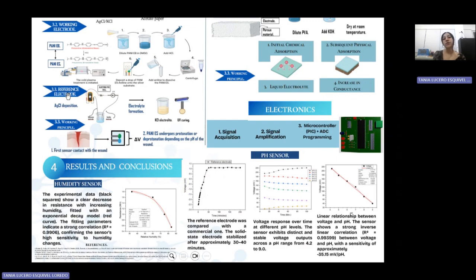Then for the reference electrode, there's a deposition of silver chloride, and from an electrolytic cell, we deposit this thin film. And then we add an electrolyte and resin solution. It's mixed and then added to the reference electrode. This is used to seal the electrode and maintain it stable and trustworthy along all the measurements.